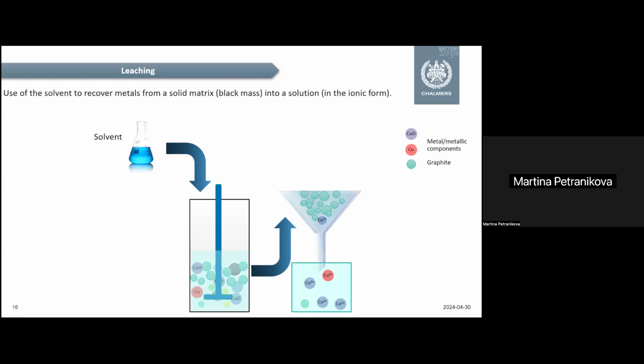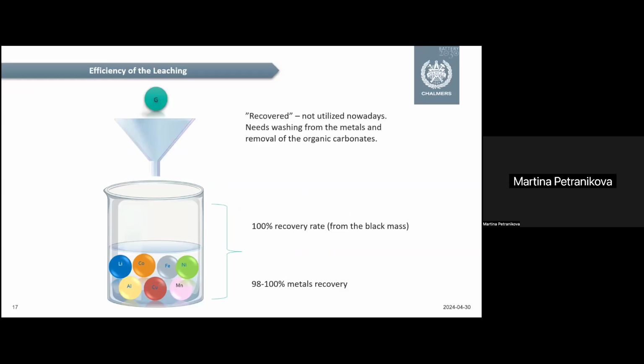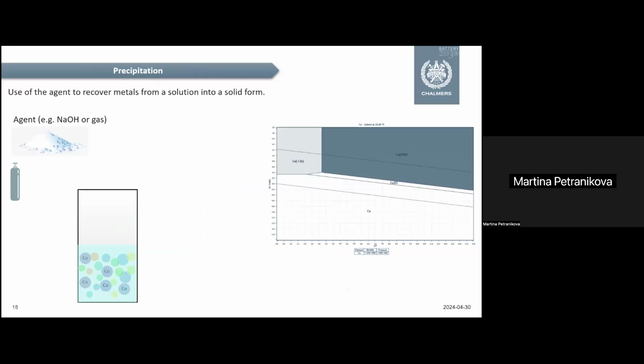And then in this step, we very easily recover graphite, because graphite is not going to be dissolved in the leaching media, which is usually acid or some base, or it can be inorganic or organic acid or deep eutectic solvent, also used these days. And this is the point where we can recover the majority of the graphite. Usually the efficiency of the leaching is very high when it comes to the metal, so we can get almost all the graphite in this solid form, and then we get all the metals in the solution. So usually this step is very effective these days.